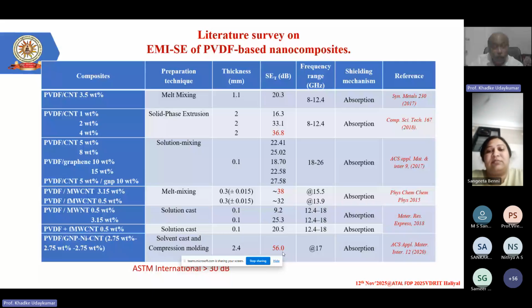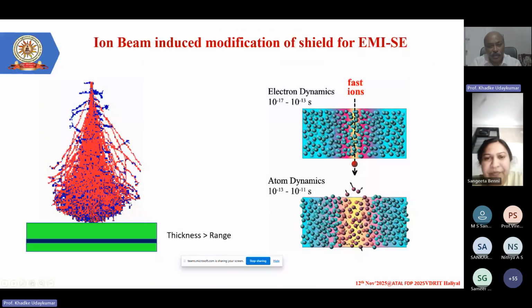when they mixed multiple types of nanoparticles in the PVDF, that is graphene, nickel, and carbon nanotubes. So a tri-type material is mixed with PVDF, and this has been modified, and they got around 56 decibel shielding effectiveness, and they showed that this is the highest value they achieved compared to what the other materials have been used. Okay, now what is the mechanism here?